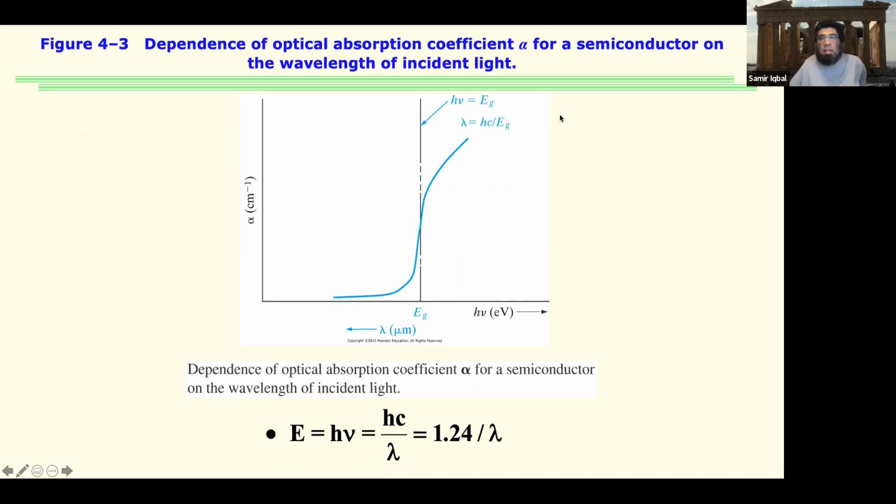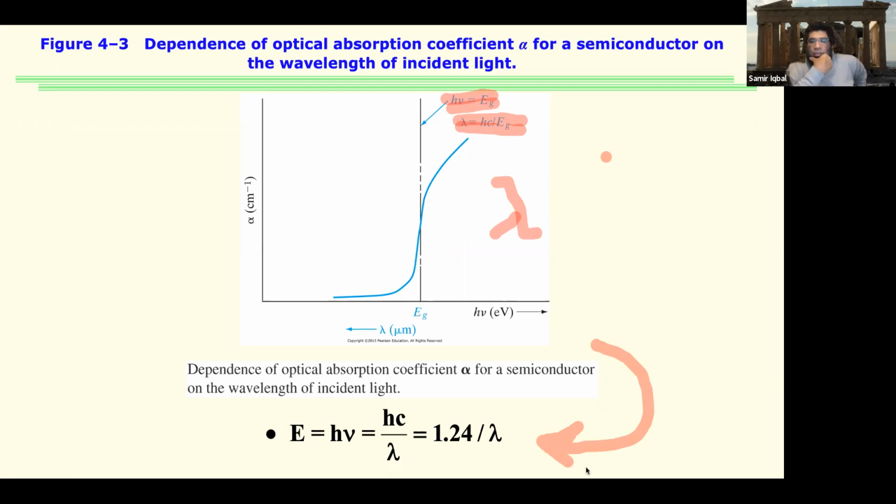It's given here: hν equals Eg, and if you put ν equals c over lambda in there, we get a way of relating lambda with the energy of the material. And if it's direct recombination, that would be the band gap energy, like it's shown here in the picture.